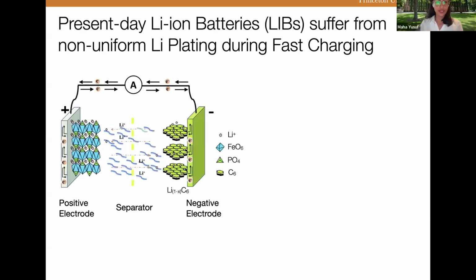However, we also know that the present day lithium ion battery technology, especially the one containing graphite electrodes and NMC cathodes and liquid electrolytes, suffers from key degradation mechanisms during fast charging. So here I'm showing a schematic of a lithium ion battery where you can see we have a positive electrode, a negative electrode, and a separator. Now, what happens during charging is we are moving lithium ions from the positive electrode through the electrolyte and separator towards the negative electrode, which in lithium ion battery is mostly graphite. And here, lithium ions then get stored between these layers of graphite in the form of stored electrochemical energy.